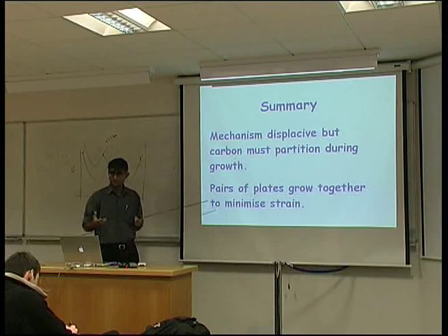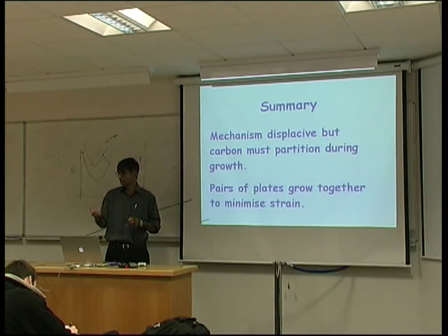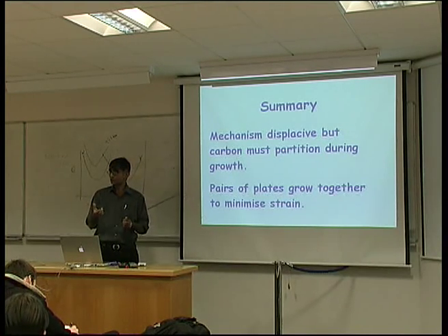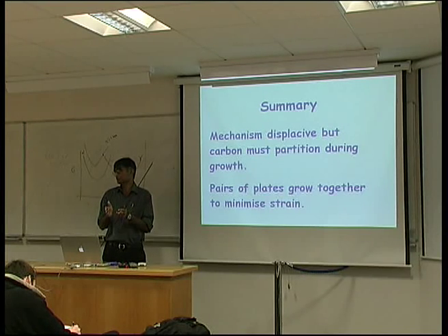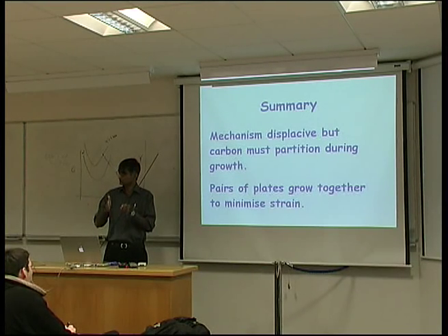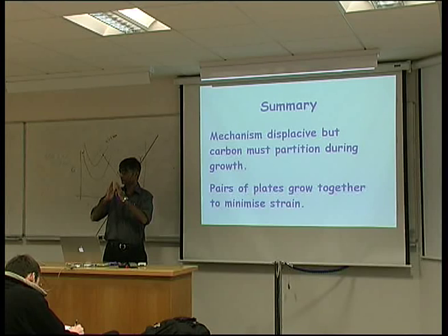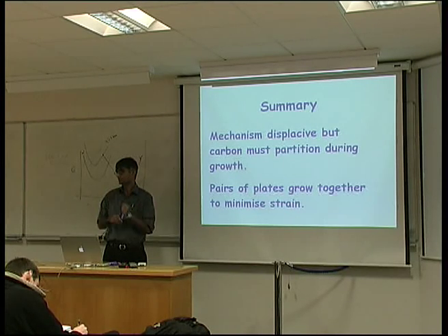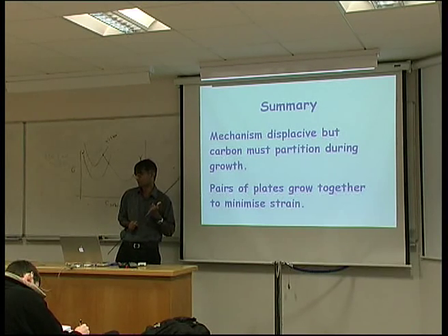And it's a clever transformation in the sense that you form a pair of plates at the same time in such a way that they tend to cancel out each other's shape deformation. And that also explains why you get a thin wedge shape. So it's a paraequilibrium transformation.